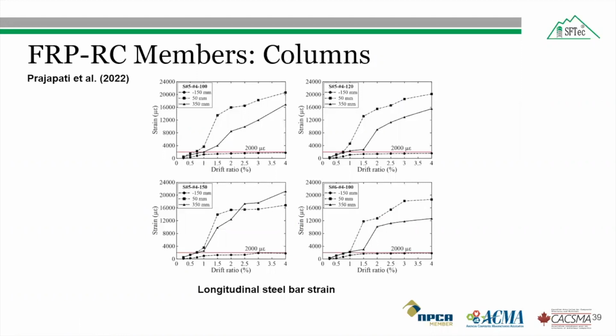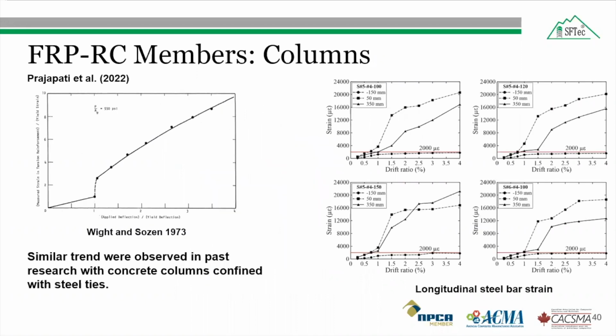The strains developed in the longitudinal steel bar at various levels above the column stub interface and below the column stub interface were compared. The strain in the longitudinal steel bar showed a jump after the yielding of the steel bar, and at 2% drift ratio, the strain hardening caused the strain to redistribute. The strain gauges installed at 150 millimeters below the column stub interface recorded strain lower than the yield strain, which showed that the development length of the longitudinal steel bar was adequate. This observed phenomenon was similar to the observation in past research for concrete columns confined with steel ties.